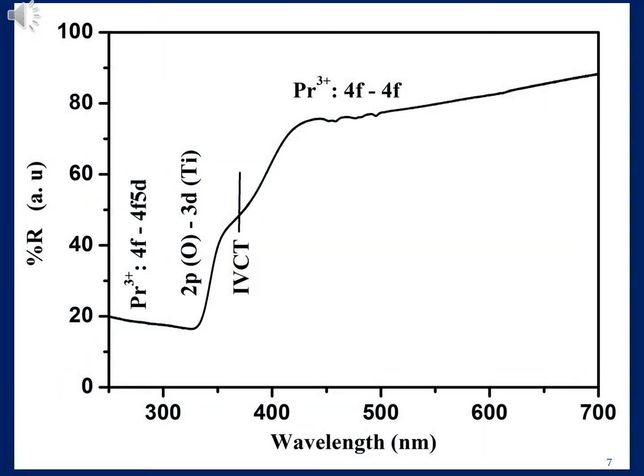Let's consider a situation when an ABO3 structure is doped with a Pr ion. Now just looking at the electronic structure, we will have a charge transfer state from A, B ion electron sharing. Now IVCT, intervalence charge transfer, and the metastates of Pr3+, the 3P, the 1D, and the 3H states, which are the most prominent in calcium titanate.